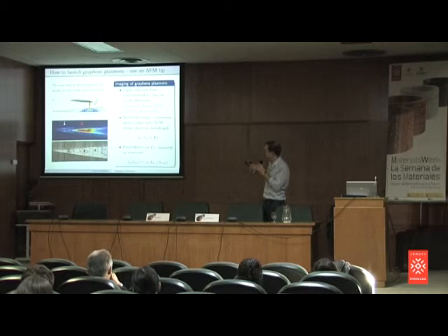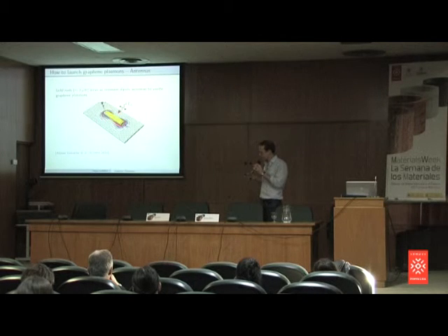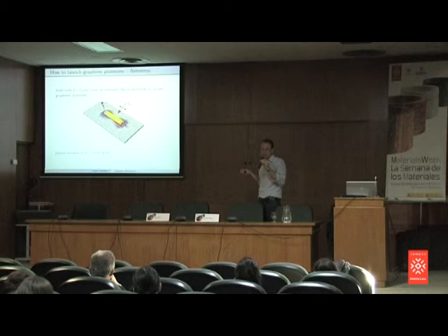But this is not practical, because if you want to build a device, you don't want an atomic force microscope to carry around. So what other people did more recently, this is again people from the ICFO mainly, instead of the AFM tip, they take a little gold particle here, 3 microns, which acts like an antenna. They put this directly on the graphene. Then they shine light on this thing. And well, then this antenna radiates in the near field, and this near field radiation is exciting plasmons in the graphene here.